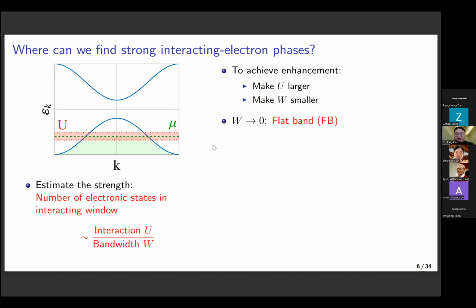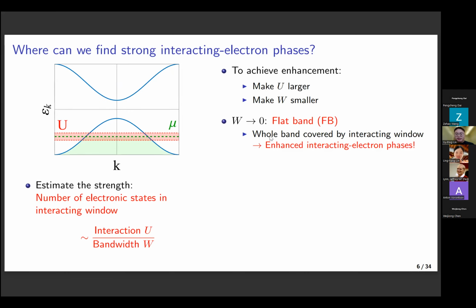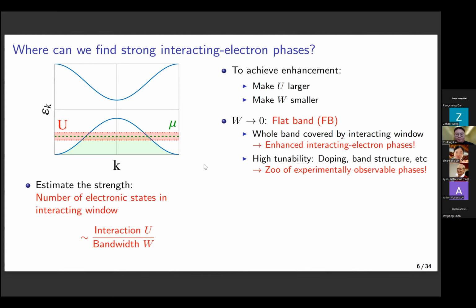So there has been a lot of interest in flat bands in the past decade. One of the reasons is that because the whole band could be covered in the interacting window, we can have very strongly enhanced interacting electron phases. And the second reason is that flat bands are usually accompanied by very high tunability in terms of doping or band structure, etc. For example, we can use gating or add a magnetic field to change the features of the system. So in experiments, there could be a large family of phases that could be observable.